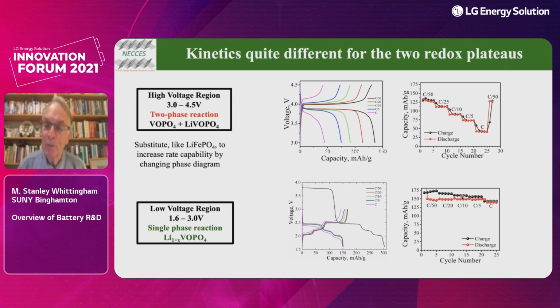On charging, we are putting more capacity in than we get out. We're getting the theoretical amount out, so we're not damaging the lattice in any way. But this material is oxidizing the solvent. So we have to find new solvents that are not oxidized by the vanadium phosphate. And this should not be a total surprise because these vanadium phosphates are used as oxidation catalysts in the petroleum industry.